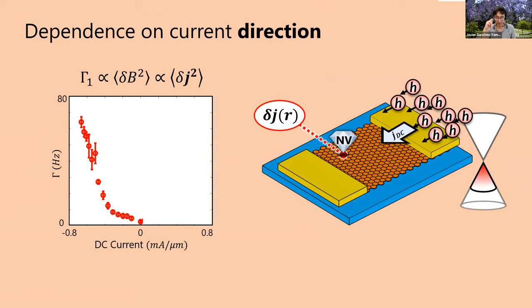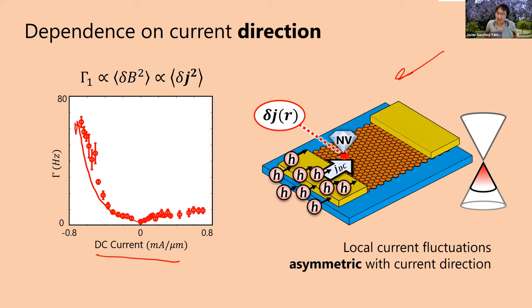Okay, so first we're going to measure the noise as a function of the direction of the current. So I'm going to have an NV center which is more towards the end of the device. And we're going to shoot hole carriers in through our graphene device, and they're going to come downstream. And what we see is that as we increase the bias of the graphene device, as expected, the current noise increases. Okay, so this is our anomalous noise signal, which we think is coming from this phonon amplification effect. And so what's important is that if we reverse the direction of the current so that now the NV center is actually sitting upstream, we don't see very much noise. So the current noise actually has a spatial profile, okay? It's very asymmetric with current direction.